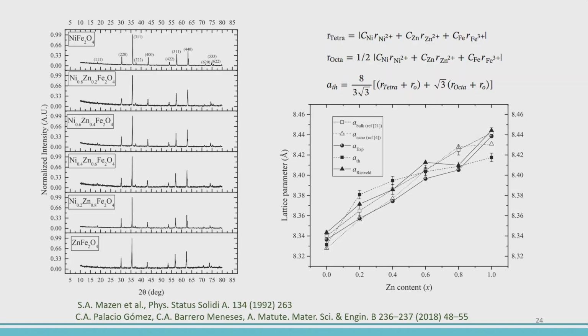So we did this. We compare this using Rietveld. We compare with the theoretical here, and we compare also determined by the Nelson-Riley method. It is also another method. It did not give exactly the same as with the Rietveld. It's not the same. And then we compare with references of nanoparticles and also with other people that prepared bulk, and this we compare.